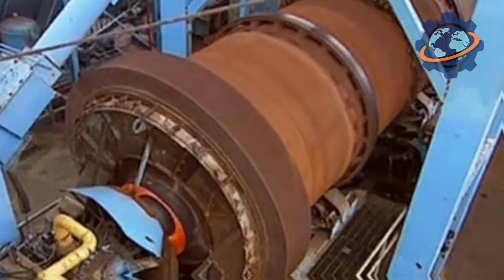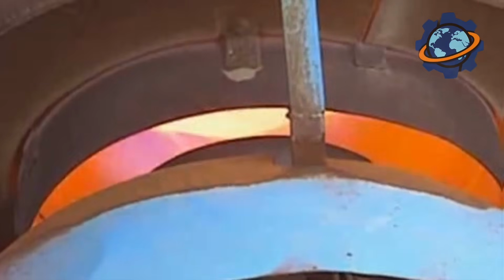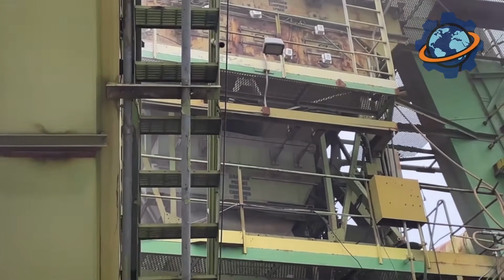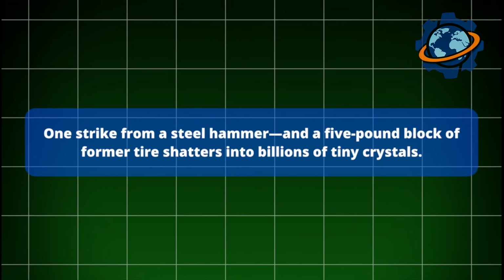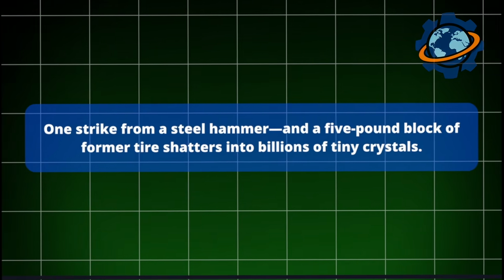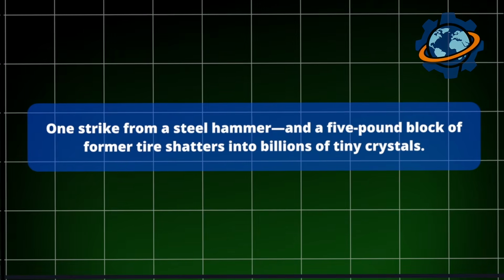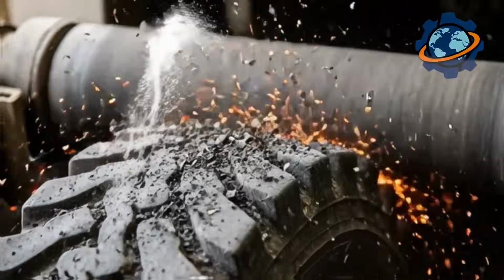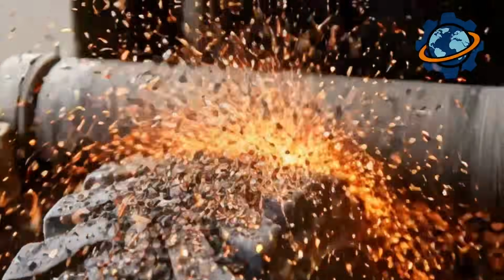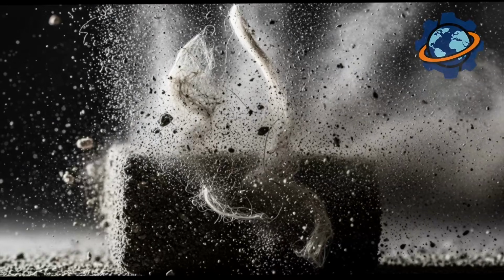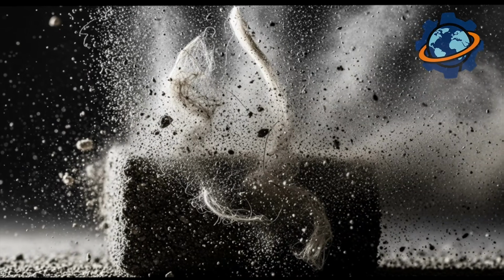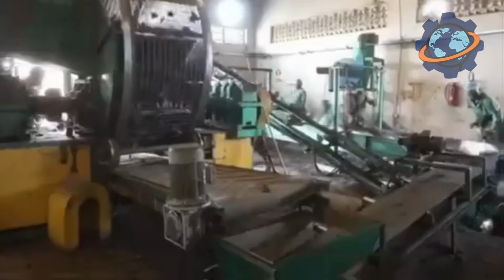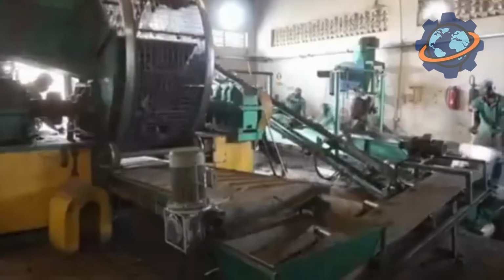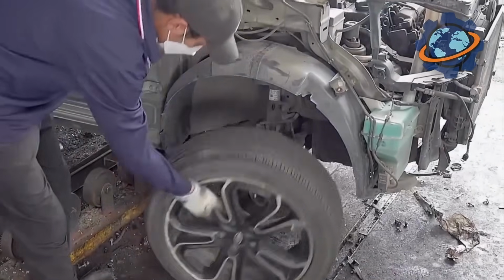This is the moment of truth. Because the rubber has lost its ability to absorb shocks, it behaves like a crystal vase. One strike from a steel hammer, and a 5-pound block of former tire shatters into billions of tiny crystals. This isn't cutting, this is total pulverization. This method perfectly separates rubber from the tiniest nylon fibers and traces of metal dust. Metal and textile don't become brittle at these temperatures, they stay intact while the rubber turns to dust. That lets magnets and air separators achieve product purity of 99.9%.